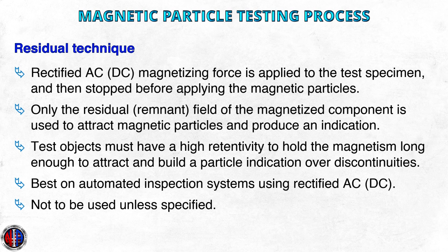However, the test object must have a high retentivity to hold the magnetism long enough to attract and build a particle indication over discontinuities. For this reason, objects with a high permeability are not suited for the residual technique. As a rule, the residual technique is most reliable for detection of surface discontinuities and best on automated inspection systems using rectified AC. Care must be exercised when removing the test object from the bath or particle spray. Rapid movement can literally wash off indications held by weak discontinuity leakage fields.